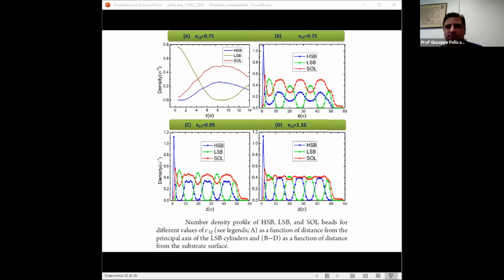Two different kinds of density profiles are shown for the cylindrical morphology cases to clearly illustrate the distribution of the solvent in the blocks. See the panel on the top left, panel A, and also the distribution of the different beads with respect to the substrate. Look at panel B on the top right. So the number density profile with respect to the substrate surface, as shown in panels B and D on the right part of this slide, displays several interesting features.